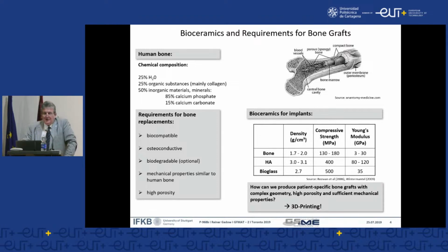I remember when I was a young researcher, one of my first theses were on the field of carbon fiber, carbon composites for prosthetic devices. So we had excellent partners on the medical side. Operations at the beginning were very successful, but the problem was this material had 10 times the strength of natural bone and also much higher elastic modulus. That means the load bearing did happen only for the implanted synthetic device, and the surrounding was not well connected, it was degraded. Because the bone has only a minimum of genetic information, it grows or it shrinks if it gets a mechanical signal that there is a load.